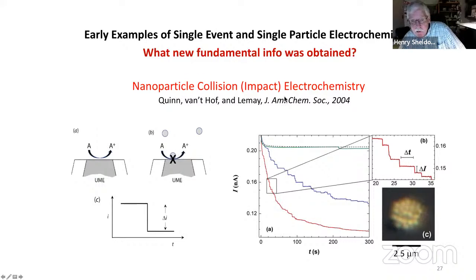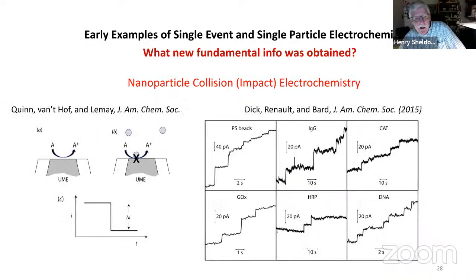This nanoparticle collision in the United States and in Europe, everywhere, in Asia, it's just been remarkable how this area has exploded. And just to show you how the technique's been refined. Instead of polystyrene particles hitting the surface and blocking the flux, you can do this if you reduce the size of the electrode from microns to 100 nanometers. Then you can start seeing things like DNA adsorbing on the surface and blocking the flux of molecules.